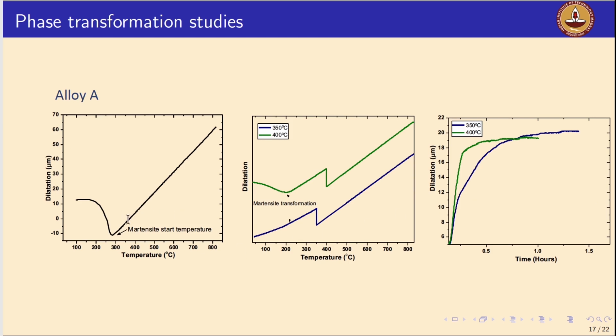If you look at alloy A, we need to first identify the martensite start temperature, MS, and we have to ensure that the isothermal bainitic holding is always above the MS temperature. The important condition, as I told you, is that whatever temperature we are holding at, and on subsequent cooling to room temperature, it should not transform to martensite. Unfortunately, in alloy A, whatever thermal cycle and isothermal bainitic holding we used, we always found some martensite transformation.